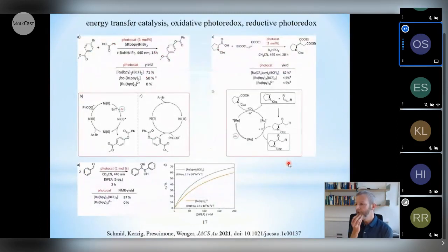And then you can look into perhaps more synthetically relevant reactions, such as this nickel-catalyzed cross-coupling reaction between an aryl halide and a carboxylate. One of the mechanistic proposals in the literature is that this occurs via triplet energy transfer to a nickel catalyst. There are also other proposals that rely more on dark cycles. The iridium complexes are typically employed for this, keeping in mind that they have high triplet energies. Rubpy does not work, but the cyanoborylated complexes again do work rather beautifully in the test reactions that we have made. That's a scenario that relates mostly to triplet energy transfer catalysis.